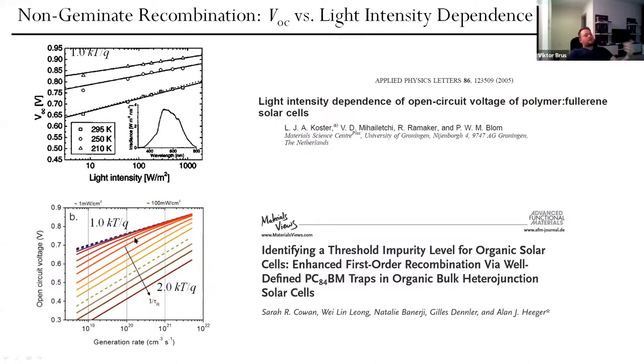However, if, for instance, we have trap-assisted recombination in the bulk, it was shown that this slope will increase, and for very high concentration of defects and some impurities in the active layer in the bulk, we will get a slope which is equal to 2kT/q. So it means if we measure this, it's quite a simple measurement.